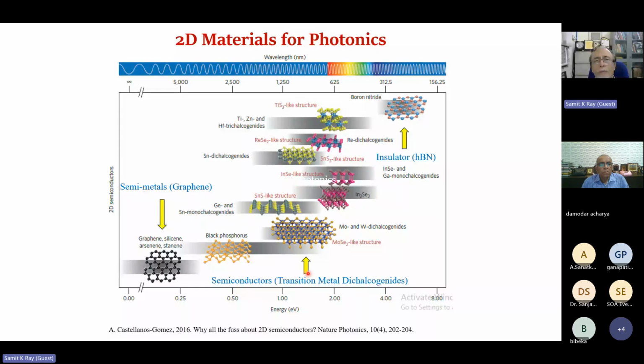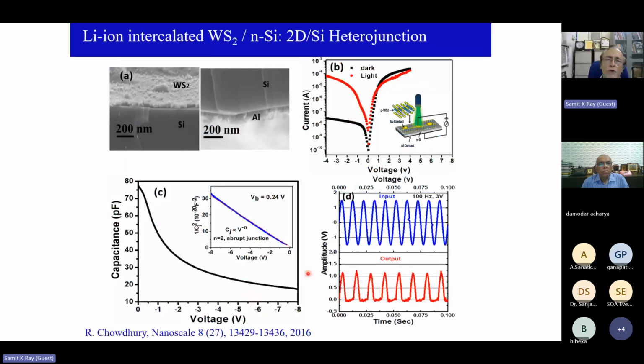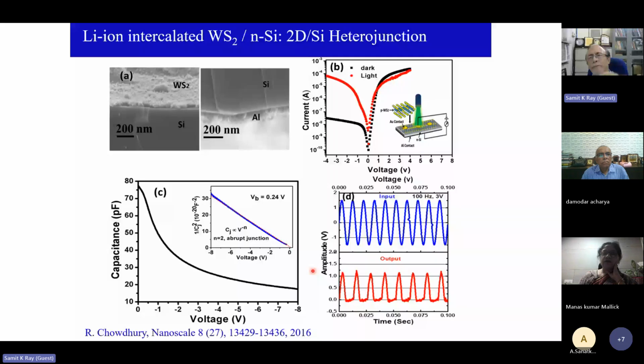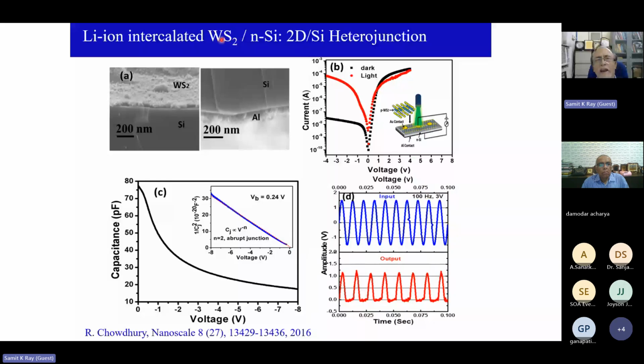So in our lab, what we have been trying to do for the last 8 to 10 years is work with different kinds of 2D materials and integrate them on silicon so that I can make a heterogeneous integration. For example, one of the works we did with tungsten sulfide, it's not necessarily monolayer, but as you see, we can take sheets of tungsten sulfide and put them on a silicon wafer, okay? And immediately we get very good rectifying characteristics that show it's a very good diode, because we take p-type tungsten sulfide and n-type silicon, it makes a p-n junction diode, and one of the properties of the diode is that it can give us a good rectifier, okay?